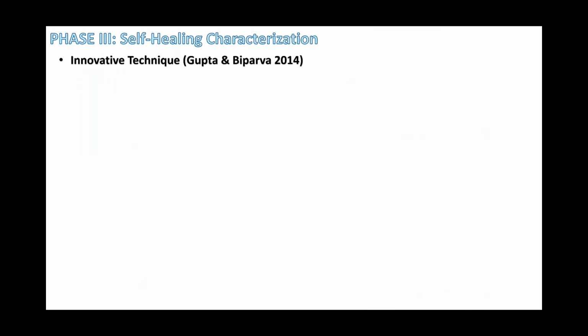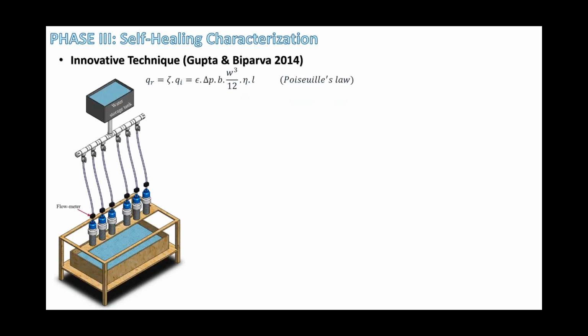Then I would like to move on to the third phase of my study, which is self-healing characterizations. Here at UVic, we developed a technique, and this technique is patented. In this technique, as you can see, we have aligned 6 cylinders on the bottom, and these 6 cylinders are similar in size to those usually used for the compressive strength test during construction on the site or even in the lab.